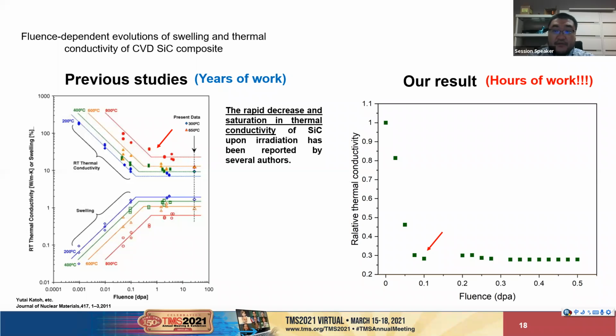At the last, I want to emphasize the result we obtained from the in situ thermal property measurement. The left figure shows the previous studies on the silicon carbide composite. Those curves are from different studies, and this summarizes all the data previously. Those data show a rapid decrease and the saturation in thermal conductivity, as you can see at the top part of this figure. This work took almost years to get all the data points.